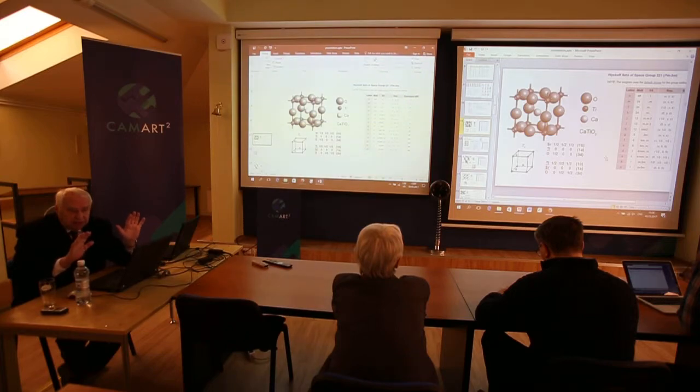and a rhombohedral lattice has 2 parameters. So lattice parameters first. Second, depending on which Wyckoff positions are occupied, you have no more parameters, or you need to add parameters if there are free parameters in the Wyckoff position. In this case, in both descriptions of perovskite, you have Wyckoff points without any parameters. So, to describe this crystalline structure, it's enough to give only the lattice parameter.